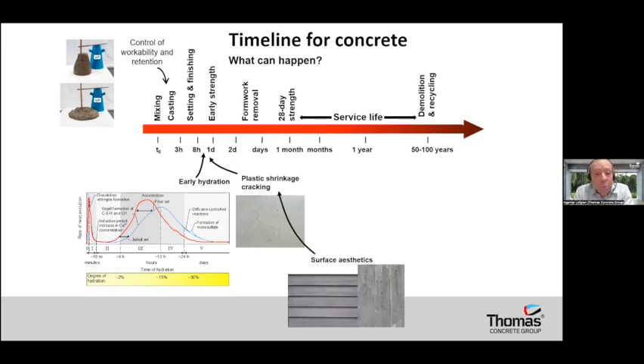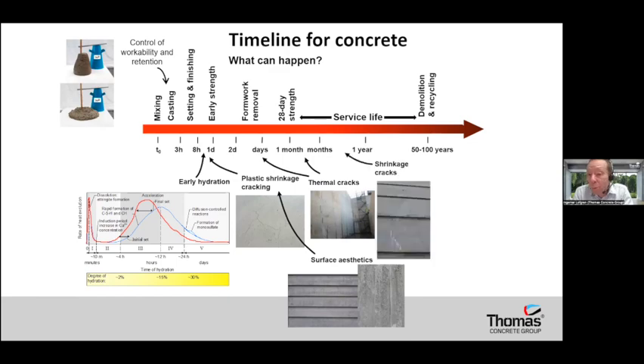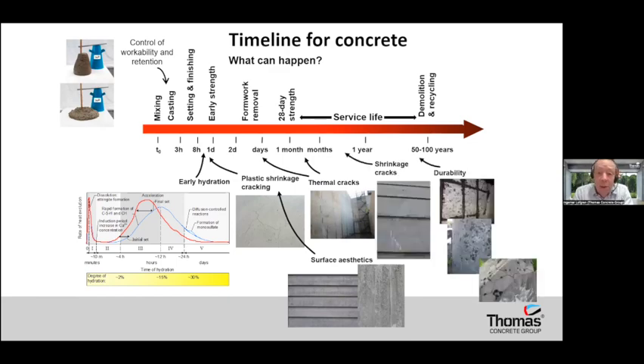If we have material that becomes retarded, for instance, we can also have problems when we remove the form after a couple of days. And if we look a bit further on, we can have problems with thermal cracking or shrinkage cracking. And in the end, what Klartje was talking about, durability of the concrete. So all this time from mixing up to end of life, we need to consider when we are looking at new materials.